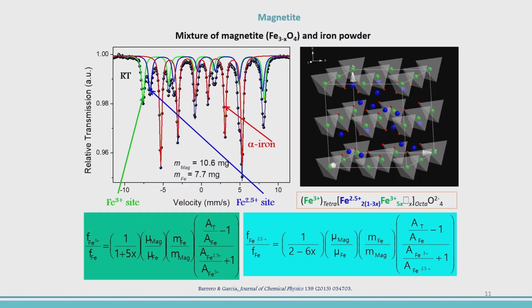And this is an example of a Mossbauer spectra of magnetite. We use 10.6 milligrams of magnetite, and it is mixed with 7.7 milligrams of iron. I have to mention that these two masses are not any mass. These masses are in the range between the ideal thickness and the thin absorber thickness. We have to work in this range. Besides, we are also correcting the spectra mathematically from the thickness effects by using software. In this case we use Recoil. So we correct this spectra from thickness effects.